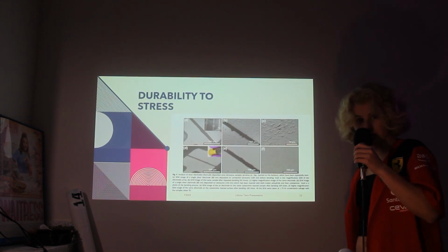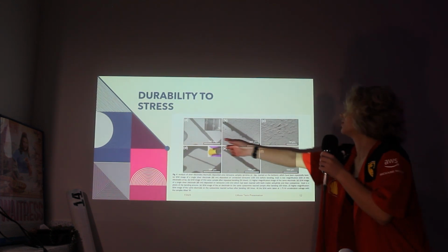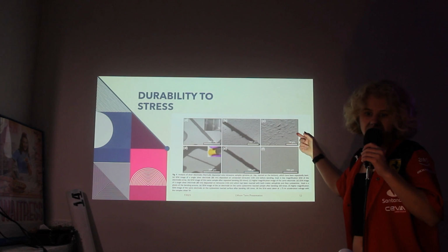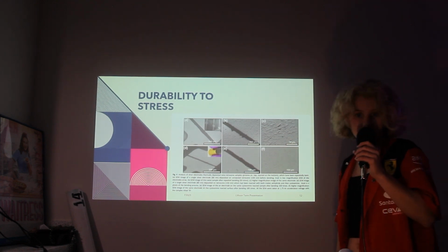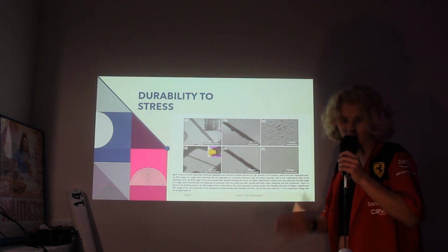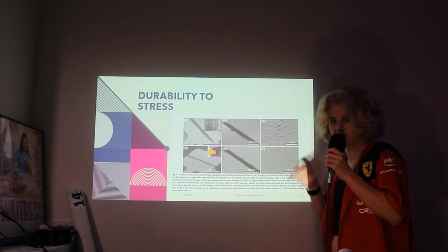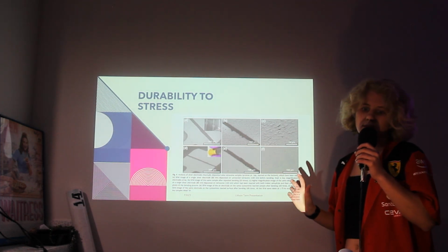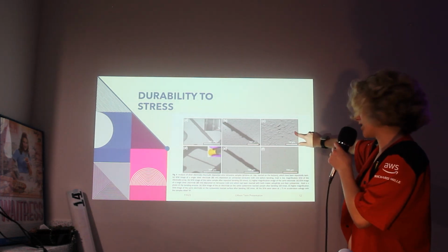You can see that the untreated samples here suffered significant delamination. They reported damage was noticeable after only 10 bending cycles and got progressively worse with more cycles until the 100 cycles were complete. The final product of that can be seen here.